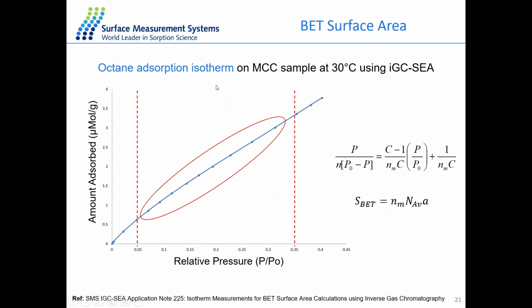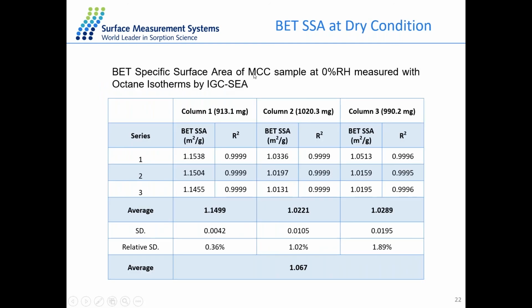So here we use octane to measure the microcrystalline cellulose sample, and we pack 3 different columns, and each column we were measuring for 3 different times, just to get experiment-to-experiment reproducibility of the measurement, to get some confidence in the IGC determination. So the average value we measure for this microcrystalline cellulose sample is just about 1 square meter per gram, a very low surface area.